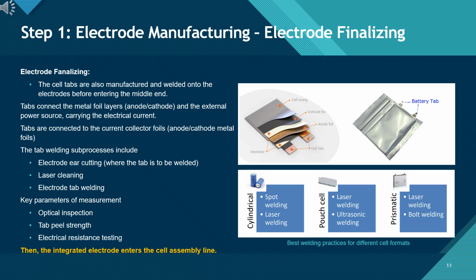We inspect the welds visually, test the tab peel strength to ensure they don't detach under stress, and measure electrical resistance to ensure the current flows efficiently. On the left, you can see a pouch cell structure where the tab is welded to the foils. On the right, the diagram illustrates the optimal welding methods for each cell type: cylindrical, pouch, and prismatic. Once tabs are attached and verified, the electrodes are complete and ready to enter the cell assembly line.